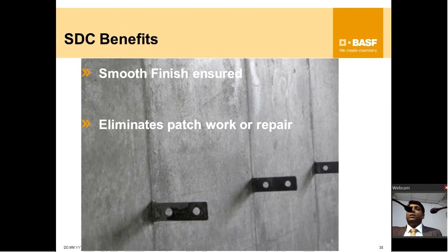If it is a flat surface where you're pouring, you have to take care of plastic shrinkage, correct? There what you need to do is spray an evaporation reducer or something like that to take care of the concrete. But the plastic shrinkage crack, we have checked, it is not as different from your regular concrete, it is almost the same. Only thing, you need to protect the concrete from heat, wind and relative humidity has to be there, and your concrete is taken care of.